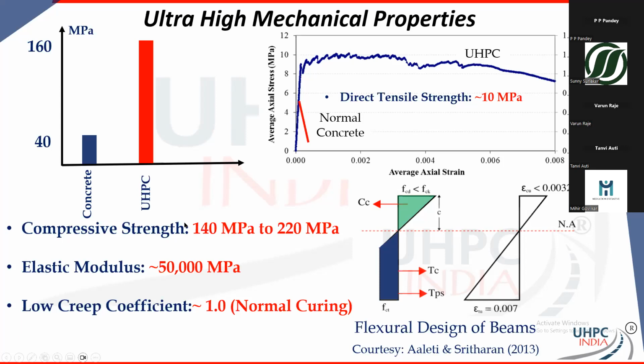Because compressive strength is good, you can put more pre-stressing. Elastic modulus is high, that helps with deflection. Creep is low, it helps with long-term, low deflection in the long-term range. Also, in terms of the ultimate design, if you take a section above your neutral axis, you don't have a parabolic curve anymore. You typically get a triangular curve now.